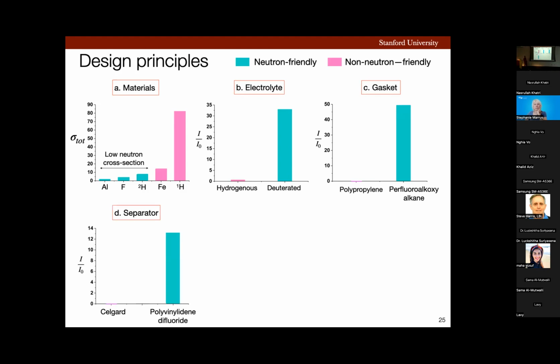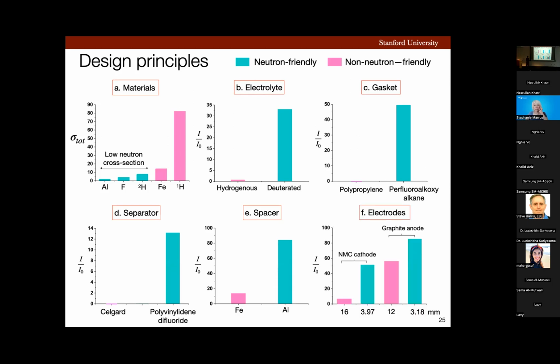Next, I replaced the standard Celgard separator, which is made of polypropylene, polyethylene, again, very high hydrogen content, with a fluorinated polymer, which increased transmission through the battery. Next, I replaced the stainless steel spacers, which are physically placed very close to the graphite anode and the separator, with aluminum-based materials to increase transmission from my region of interest. And lastly, I made my electrodes really small.